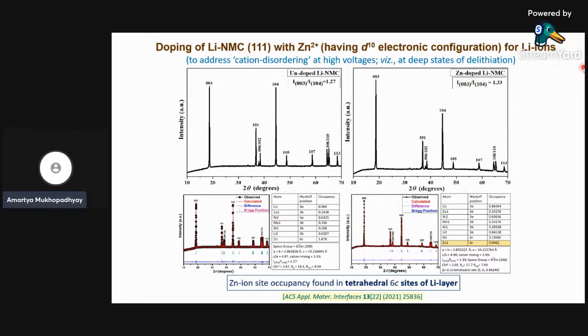So now, in one of our recently reported works, we tried to address this problem of cation migration from the transition metal layer to the lithium layer by putting something in the intermediate tetrahedral site. Zinc, having a d10 electronic configuration, does not have a preference for octahedral or tetrahedral sites. So it can actually go to the tetrahedral site of the lithium layer, and that is exactly what we tried to do. We substituted a little bit of lithium with zinc and found, based on characterization and analysis of the structure, that zinc actually occupies the tetrahedral site of the lithium layer, which otherwise serves as the intermediate site for the nickel migration.